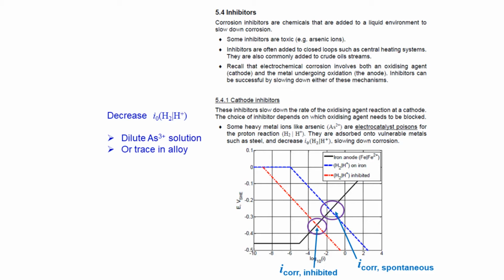Now, we have here an Evans diagram, and if you look at the intersection of the black line, this is the iron dissolution reaction, that's an anode, and consider first spontaneous corrosion, where we look at the intersection of the iron dissolving anode with the hydrogen cathode taking place on iron spontaneously. If we find the intersection of those two lines, we find the current density for corrosion, and if we want it, also the mixed surface potential.